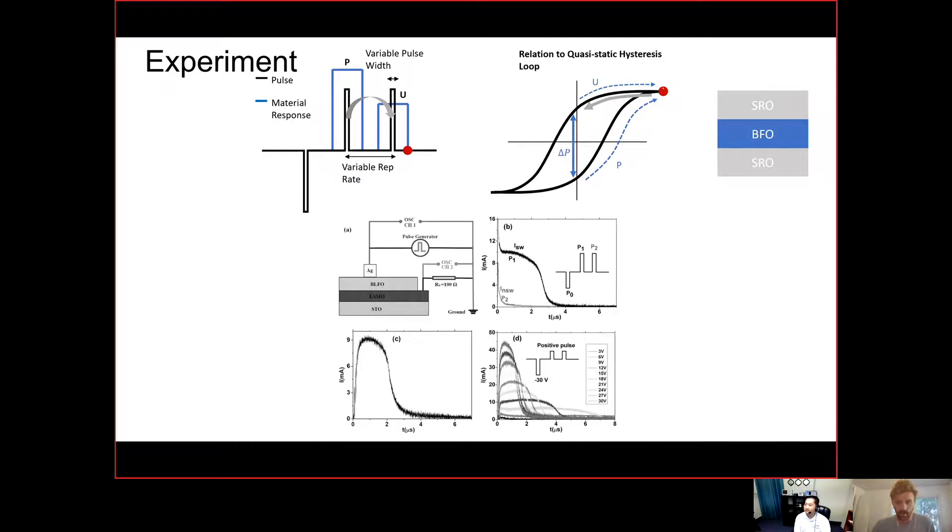Let's just say that I have - I'm going to basically trace out this hysteresis loop. So what I'll do is I'll apply some negative voltage, and that will preset my polarization in a well-defined state. By applying that negative voltage, I preset my polarization to the negative state. Now I apply a sequence of two up pulses. The first up pulse will switch the polarization. I'll let it relax to what I call the remnant state. And then I'll drive it again with an identical up pulse, which will not switch the polarization, but will enable me to look at how the material responds when there is no switch. So the key here is that in the first up pulse, switching response plus some other dielectric or other types of material responses. And in the second pulse, I only have the material or the non-switching response. So what I can do is I can subtract the response to the first pulse minus the response to the second pulse, and that gives me just the switching response.